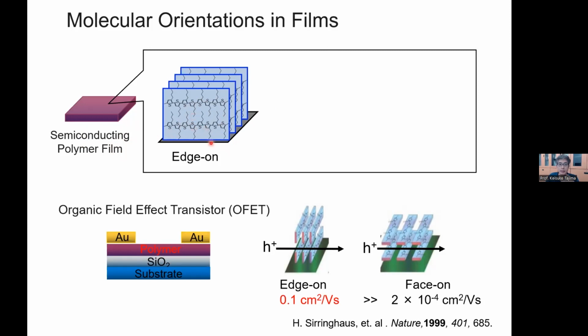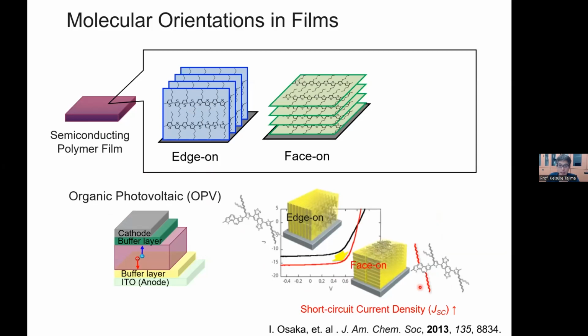For example, if you imagine this, we call it the edge-on orientation, where the polymer chain is aligned parallel to the substrate, and the pi-plane is perpendicular to the substrate. In this case, this seminal early work by Sirringhaus showed that the charge transport in the organic field effect transistor is really affected by this molecular orientation. This edge-on is better than this face-on, where the pi-plane is parallel to the substrate. If you change the orientation like this, mobility in this direction is largely different. This one is much better than this face-on. So molecular orientation, edge-on, is better for the organic field effect transistor application. On the other hand, face-on is better for the organic photovoltaics or solar cells.